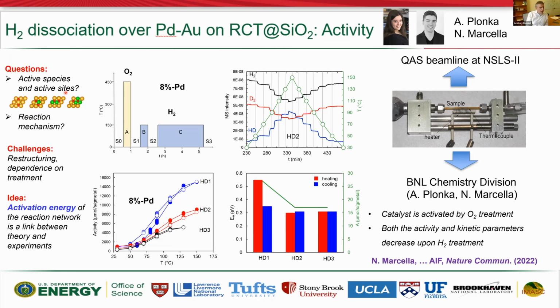And so the challenges are, of course, that not only is it a dilute catalyst, we don't have a very clear way to detect the position of palladium on gold, and we knew that the answer depends on the knowledge of that. We also know that it may restructure in reaction conditions. It may restructure in the pretreatment process, and I already showed you the evidence that it does. And therefore, it's a very dynamic system, and it's very difficult to analyze by conventional methods, especially if you don't know the structure. So our approach was, just like I showed you in that schematic, let's link structure, activity, and theory together. And in order to understand the structure, we will use this machine learning assisted XANES, because there is no other resource of structural information. You can't get the structure of dilute palladium and gold by any other tool in reaction conditions.